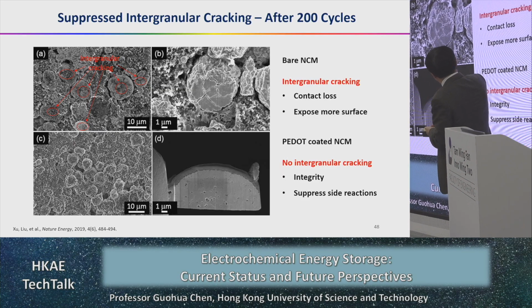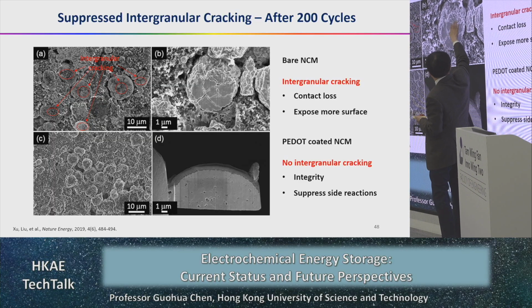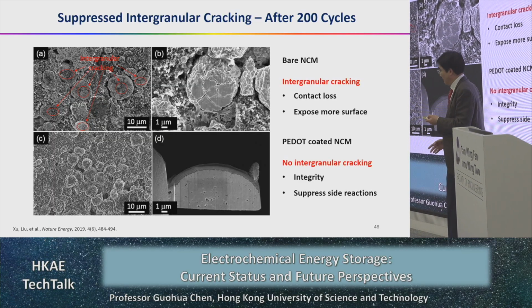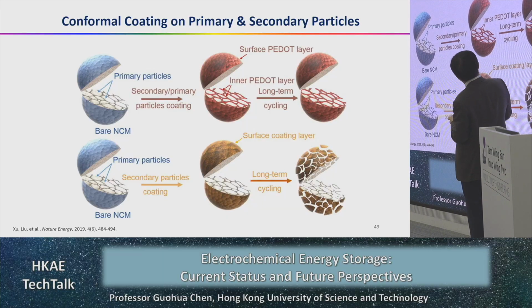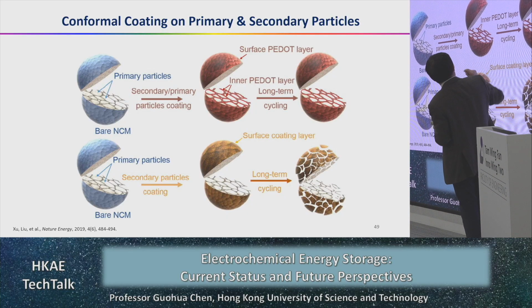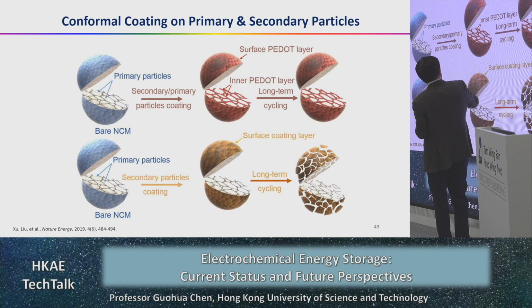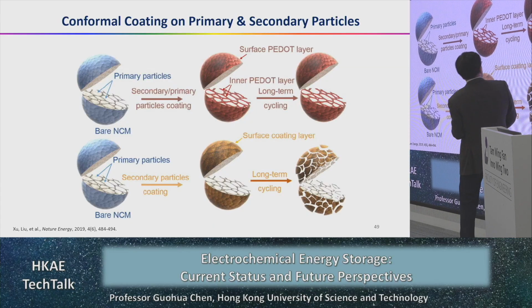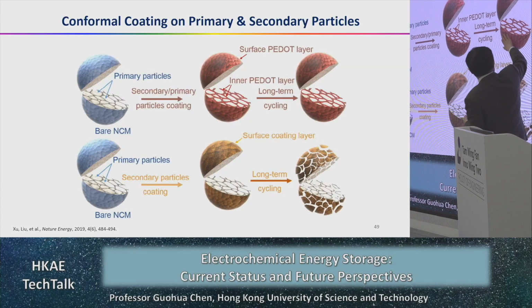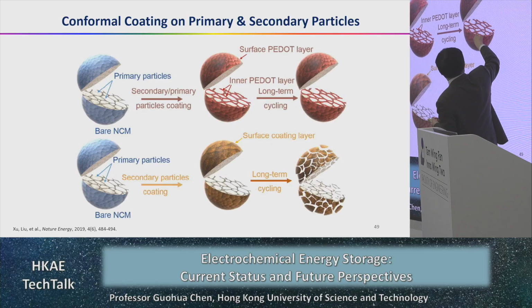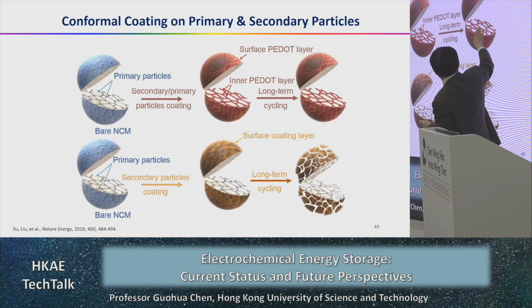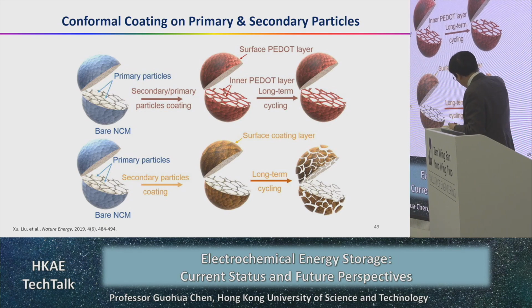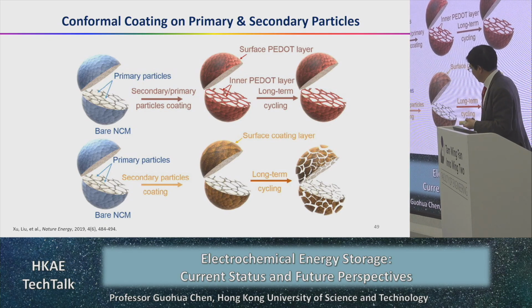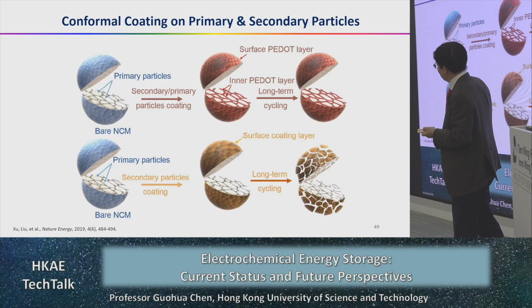And you see that without coating, you have the cracks. With coating, not. And the reason is that with our CVD type of coating, not only do we coat the outside, but also the vapor can get to the inside of the particles. So the boundaries of the particles are all well coated, instead of only the outside surface like most other coatings. This is the reason.